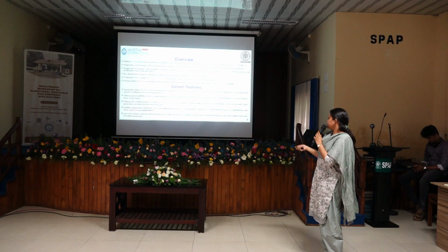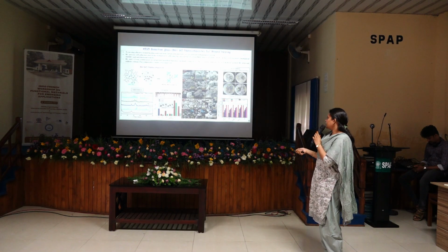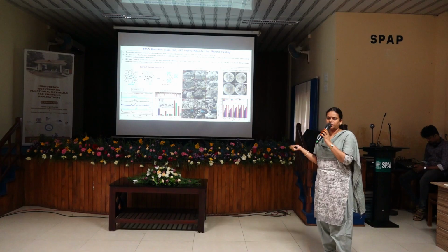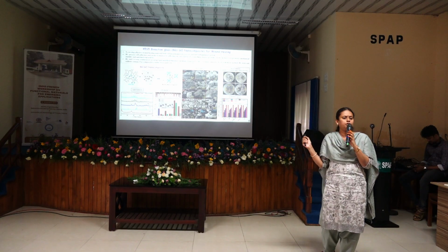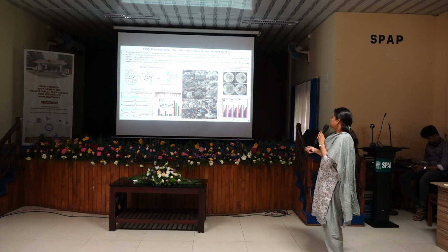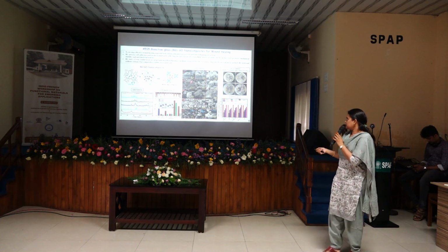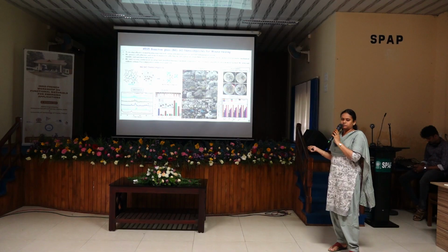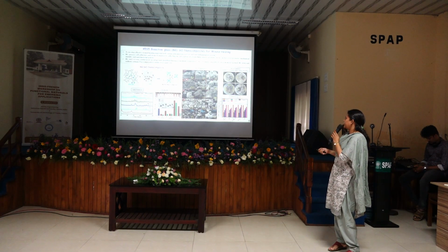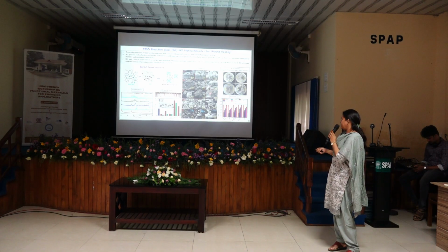So here, for the bioglass with sodium and without sodium, the XRD showed a calcium silicate phase and a sodium silicate phase, with silicocarnotite and a combined phase. Further, the SEM studies show that as the bioglass has different metal ions, it shows different morphologies like spherical, flake-like and also sheet-like rod types.